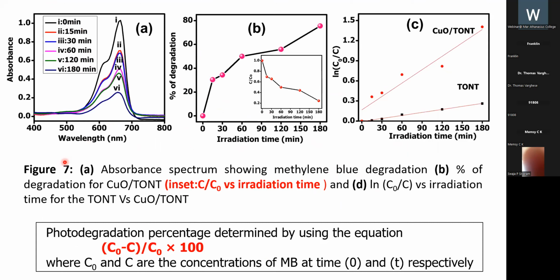It is seen from figure 7 that within the time span of 180 minutes, about 75% photodegradation of methylene blue is achieved for the active solution. A maximum of 5-fold increase in the degradation rate for methylene blue is obtained with CuO TON compared to pure TON.